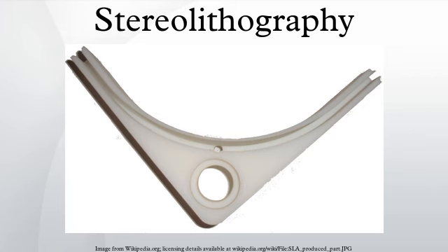After the pattern has been traced, the SLA's elevator platform descends by a distance equal to the thickness of a single layer, typically 0.05 mm to 0.15 mm. Then, a resin-filled blade sweeps across the cross-section of the part, recoating it with fresh material. On this new liquid surface, the subsequent layer pattern is traced, joining the previous layer. A complete 3D part is formed by this process.